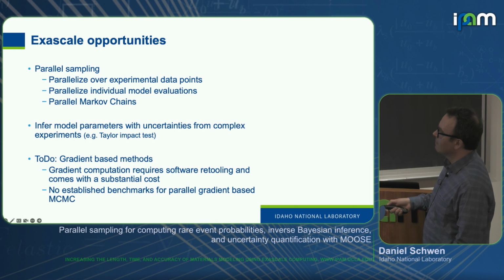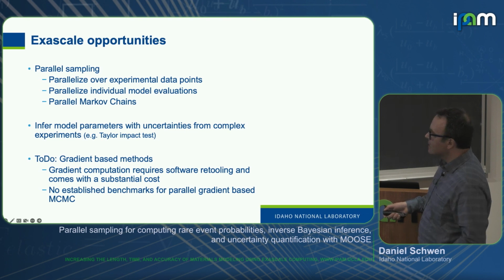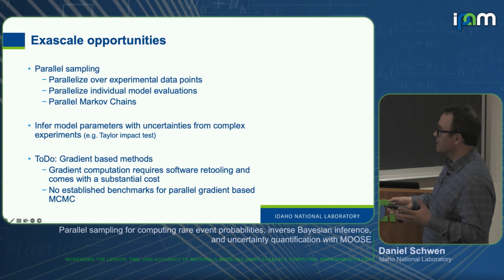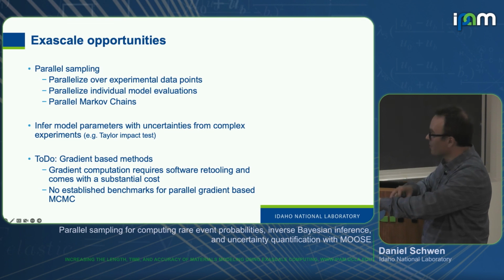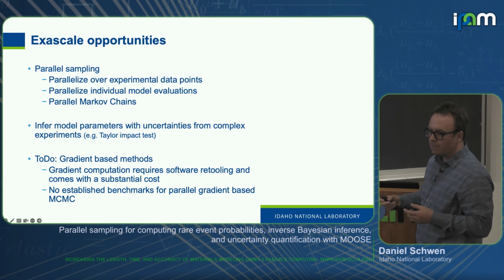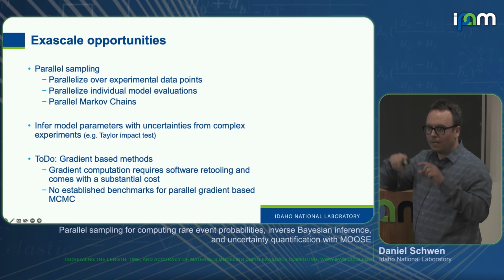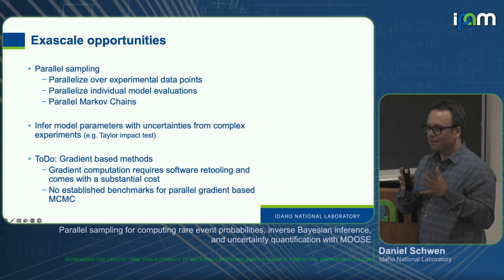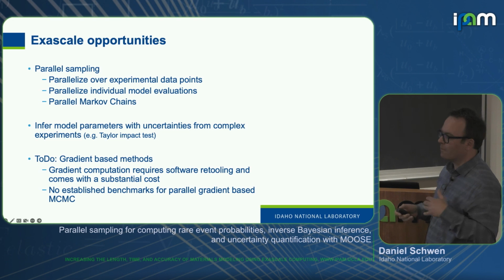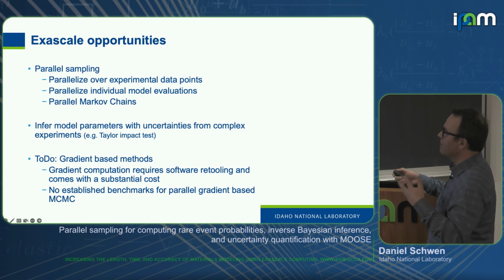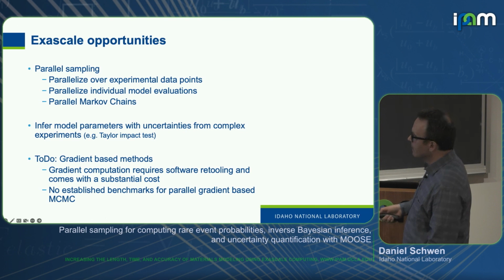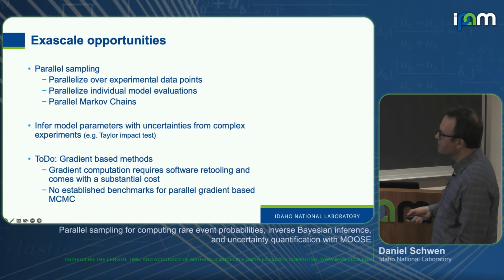We could, for example, easily get estimates for the prefactors. All right. Exascale opportunities: parallel sampling will allow us to really trivially parallelize and burn a lot of CPU hours. We can infer model parameters with uncertainties from more complex experiments if we have more computing power. So one of those projects that I should be currently writing a proposal on is Taylor impact tests, where you shoot a little metal bar at a wall and then you look at how it mushrooms up, and that gives you an integrated way of checking for the high deformation rate plastic response of a material, and it would be really cool to parameterize models from those tests.